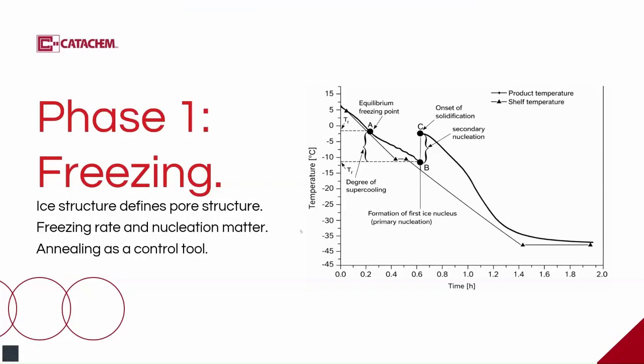So what really matters in freezing? Freezing rate and nucleation. And what is nucleation? As ice forms, the water molecules cluster to make nuclei, or seeds, from which larger ice crystals grow. The more controlled this is, the less haphazardly the ice crystals form, and the more uniform the process and the final freeze-dried product. Final freeze temperature and hold time is important. Whether the formulation benefits from annealing is also important. So what is annealing? Annealing is the process in which a gentle heat step is added after the initial freeze to regulate ice crystal size before refreezing.